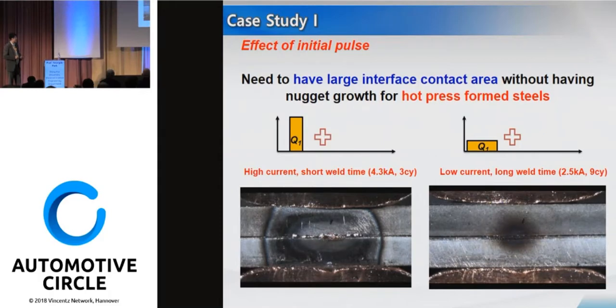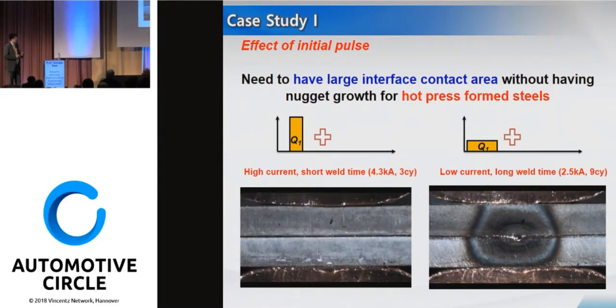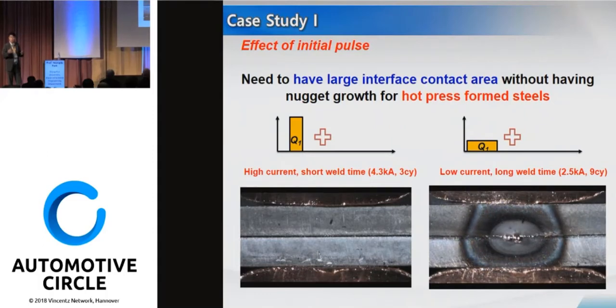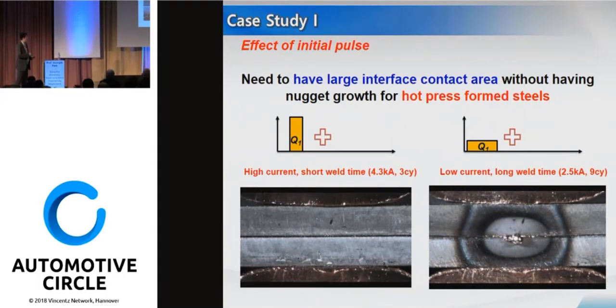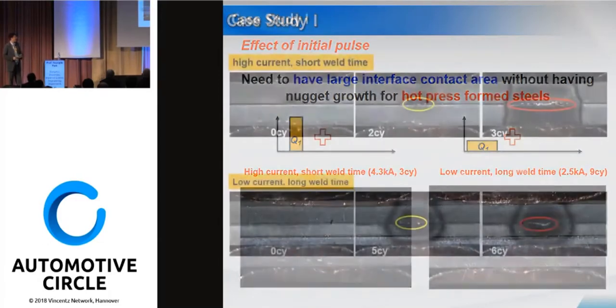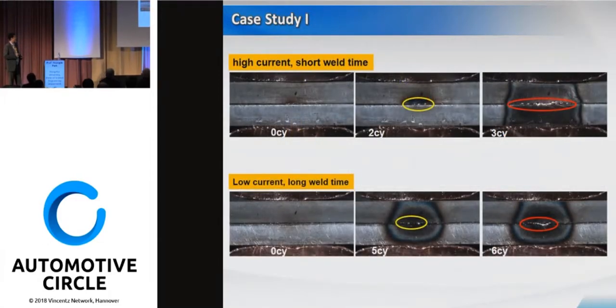Yes, now it's starting. With low current, the contact area between the faying surfaces is increasing, but not as much as in the high current case. So I captured the image between the high current and low current. You can see the difference very clearly. In the case of high current and short welding time, you will have a large contact area without growing a large nugget in high strength steels.